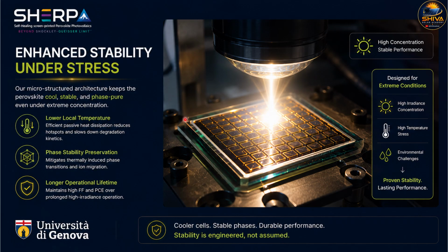Here we move from efficiency to stability, because for perovskite devices, surviving under stress is just as important as achieving high performance. Here you can see the microstructure device operating under intense concentrated illumination. Normally, this level of irradiance creates severe thermal hotspots and accelerates degradation. But as our test results show, our architecture changed this behavior.